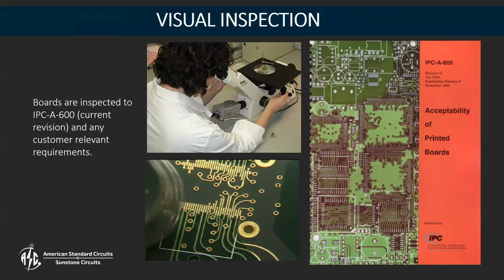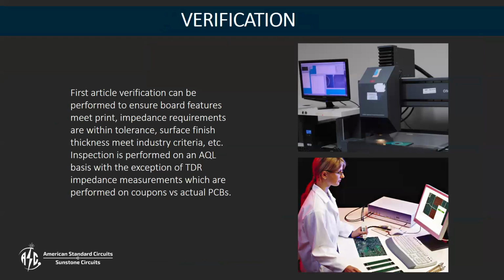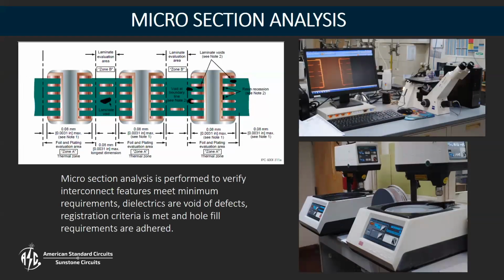Boards are inspected and getting ready to be bought off for a clean bill of health. We utilize the IPC-A-600 as that visual standard, as well as cross sections, et cetera, based on 6012 or 6018, depending on your design. Verification, whether there's impedance testing or anything else that's done, CMM verification of the tolerances and the dimensions are done there as well. Cross sections, where required, are done as well, so we can see what the internal part of the board looks like, the copper thickness inside the holes, whether there's any laminate voids after reflow.